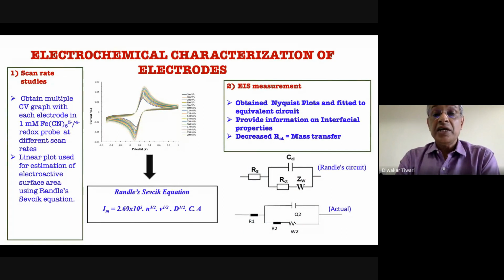Then the electrochemical characterization that we have done, in two ways. One way is the scan rate studies, where we excite the electrode by increasing the potential at different time intervals, and that is called the scan rate. The scan rate was increased from 50 to 200 millivolts per second, and using the Randles-Sevcik equation, we could get the electroactive surface area. On the right-hand side, you can see the EIS measurement, the impedance spectroscopy. Through that, we get the RCT value, which is related to the mass transfer reaction taking place at the surface, using the Randles circuit or equivalent circuits.